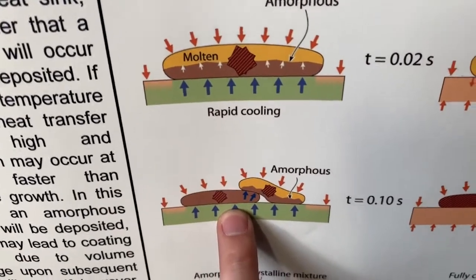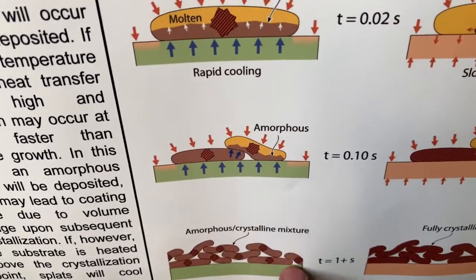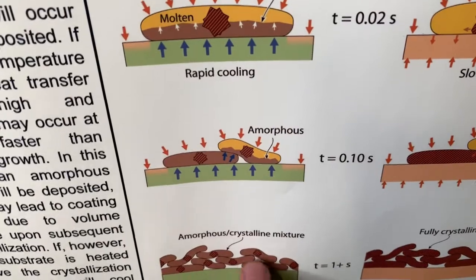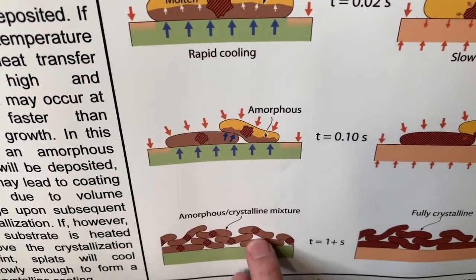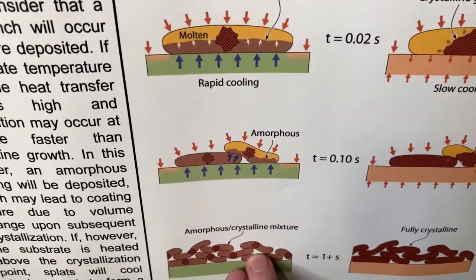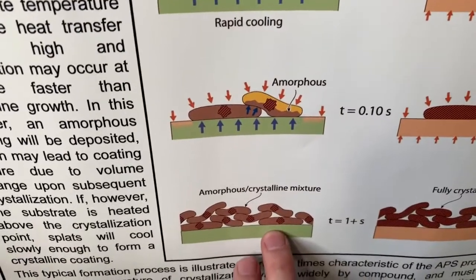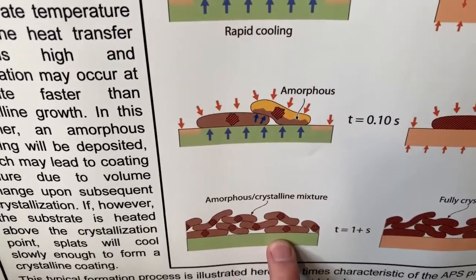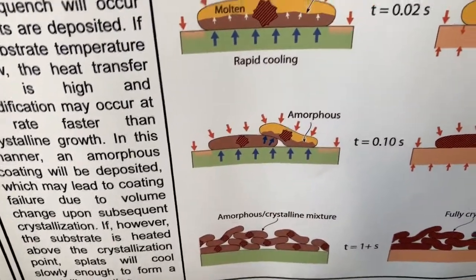Then when this happens multiple times, eventually you get a layer of material that can be partially porous and also semi-amorphous or semi-crystalline. And that is something that you don't really want, because once you heat it up again, it will start to crystallize and it will start to transform.